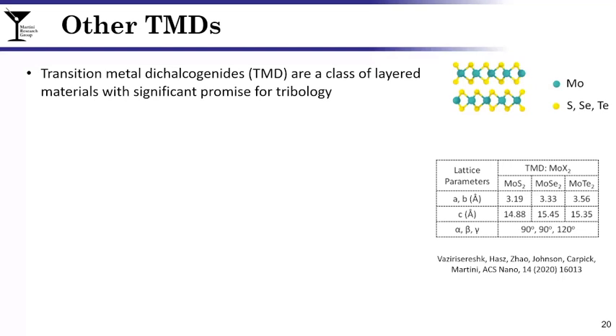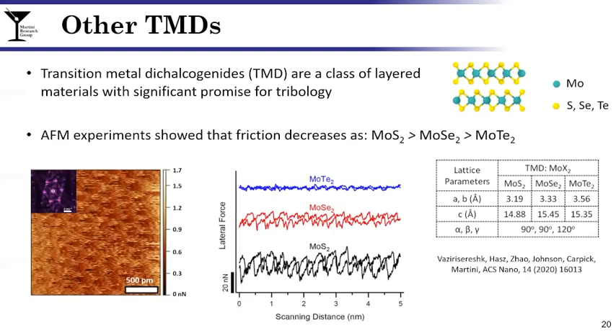You can see here the lattice parameters on the right. They have the same crystallographic structure with slightly different lattice spacing. So now we're removing some of the possible reasons for differences, and we're isolating it to just the lattice parameter. Shown here are the AFM results. On the far left, we see a friction map with atomic stick-slip features, indicating indeed our friction can be correlated to atomic properties.